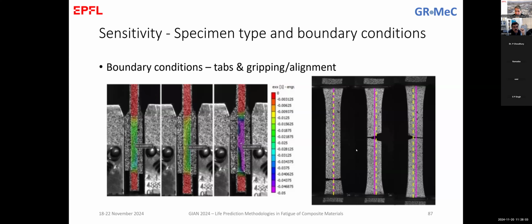The second thing that we observed is that... Yes, I have a small query. Yeah, like this tab failure and temperature rise in the tabs. We have seen that this phenomenon is very, very persistent, specifically in materials which have very high stiffness. We were testing a few samples of very highly stiff glass fiber composites for wind turbines, and we observed that most of the samples are failing in the tabs. The failure region is the tab region in almost 90% of the samples, with too much temperature rise.